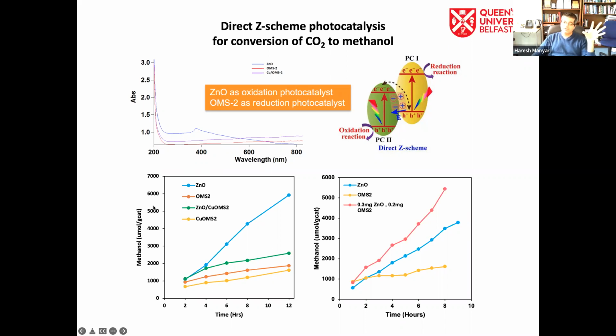On the left-hand side here, you can see production of methanol, which is much better than what we can see in the literature. The reaction on the left-hand panel is done using just UV light, and zinc oxide is performing best here. But on the right-hand side, we moved from individual metal oxides to the mixed metal oxide, so we moved to the direct Z-scheme. And here we are shining two lights, the UV light as well as red light. With the combination of the two lights, we can see that with the mixed metal oxides the performance is much better compared to the individual zinc oxide or manganese oxide.